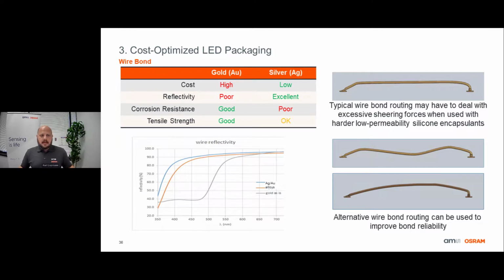Now, the primary purpose of the wire bond is to electrically connect the LED die to the lead frame. When it comes to the alloys that are selected, there are several factors that need to be considered, such as corrosion resistance, strength, reflectivity, and cost. And like most things in life, there are trade-offs and compromises that need to be made. While gold offers superior corrosion resistance and tensile strength over silver, it comes at a cost, literally, and exhibits poor reflectivity at wavelengths below 500 nanometers, as you can see in the bottom left. And this, of course, is a big issue, as the typical pump wavelength for white LEDs is 450 nanometers.